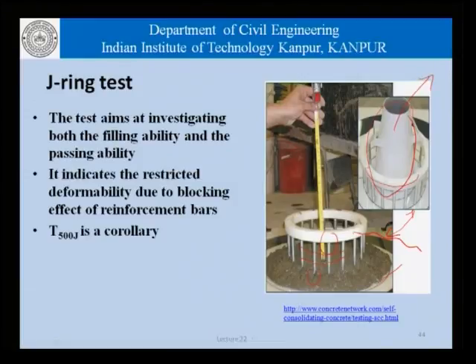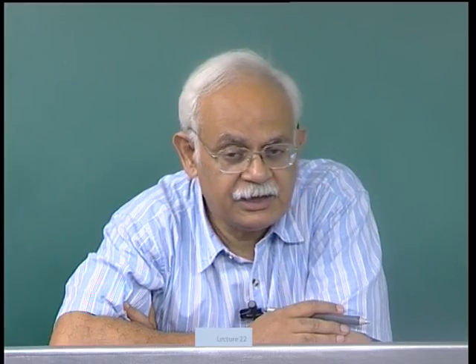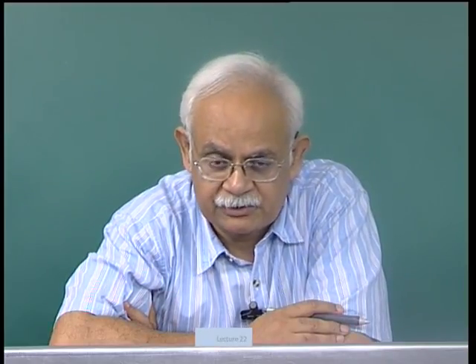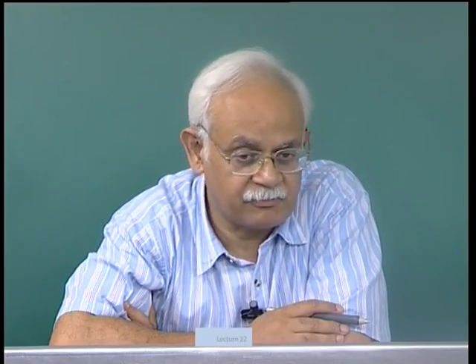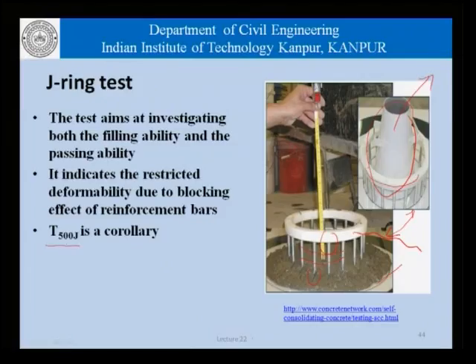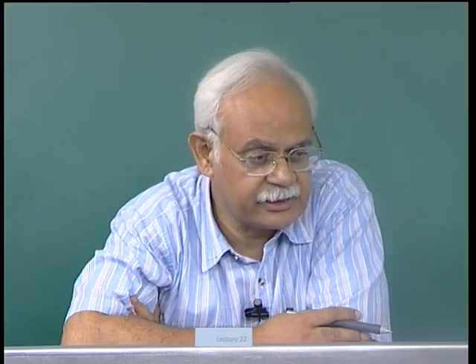A variation of the T500 time that we talked about when we were talking about a corollary to the slump flow is the T500J. The T500J is the time that it takes for the concrete to achieve a diameter of 500 millimeters when tested with a J ring.